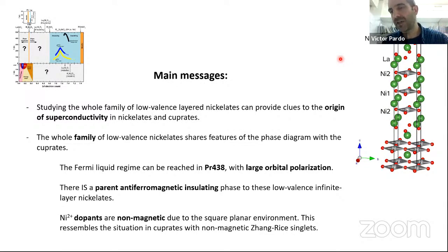So what we see from those calculations, which are really toy models, is that what brings about the hugely dispersive band is the nickel d_z² continuity along the c-axis that exists in the neodymium nickel O2. But when you compare that solution with the cuprates, certainly the oxygen p bands are much lower in energy by 2 or 3 electron volts, and that was calculated by Antia Botana and Mike Norman. And it is similar in the monolayer.